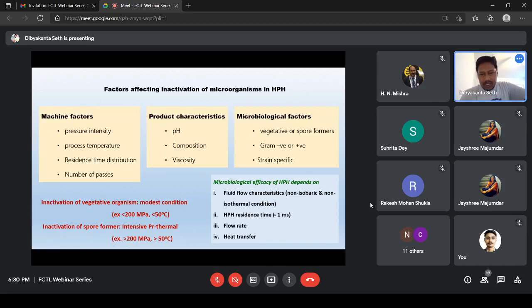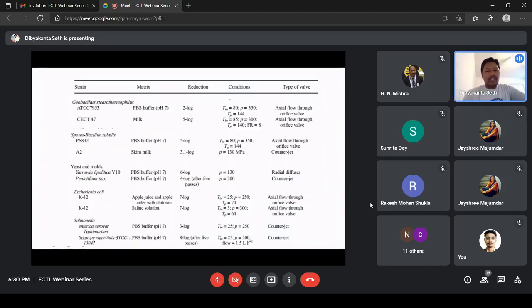As I mentioned earlier, it depends on the fluid flow characteristics, HPH residence time, flow rate, and heat transfer, and heat transfer is also dependent on the flow conditions, like whether turbulent flow or cavitation is predominating. So enormous research has been done on the killing of bacteria. Geobacillus stearothermophilus is considered one of the most pressure-resistant bacteria. There is a 2 to 5 log cycle reduction with this particular condition, pressure above 350 or 300. What type of valve can we use?